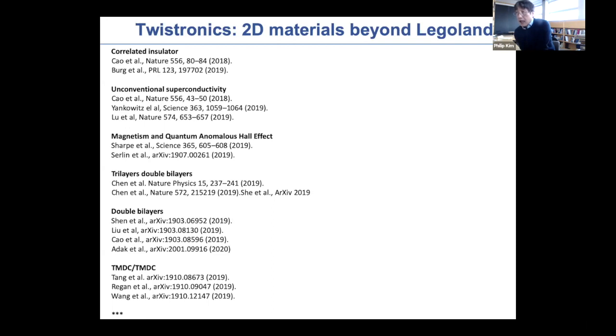And there's also not only the magic angle twisted bilayer, but you can put two Bernal-stacked graphene bilayers together to form the so-called twisted double bilayer. And there has also been a demonstration of correlated insulating behavior, plus some sort of spin polarization of the correlated gap and potential superconductivity, and those kinds of things have been reported by many experimentalist groups. And also as Alan mentioned, now not only graphene-like systems, the system has expanded into TMDC, the transition metal dichalcogenide systems, either homojunctions or heterostructures with very similar lattice parameters.